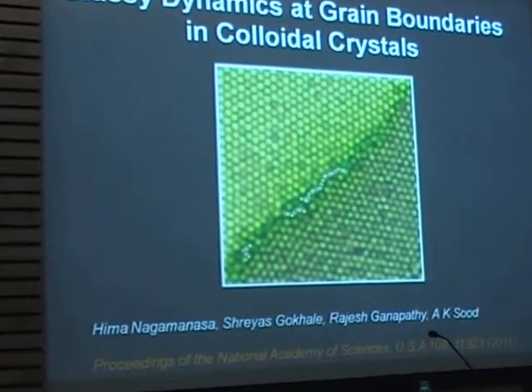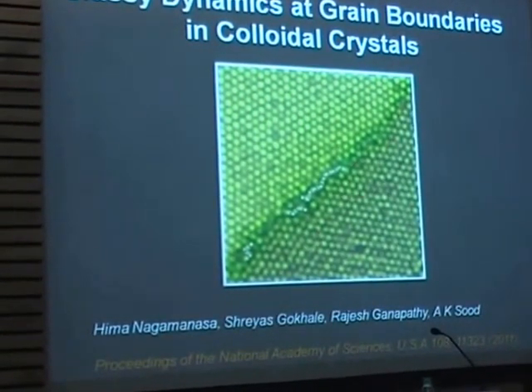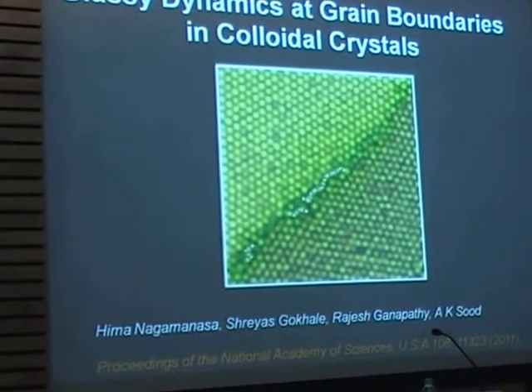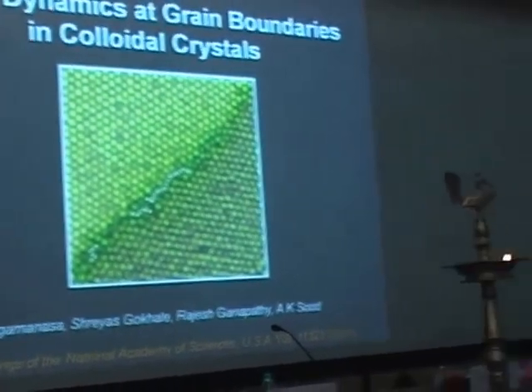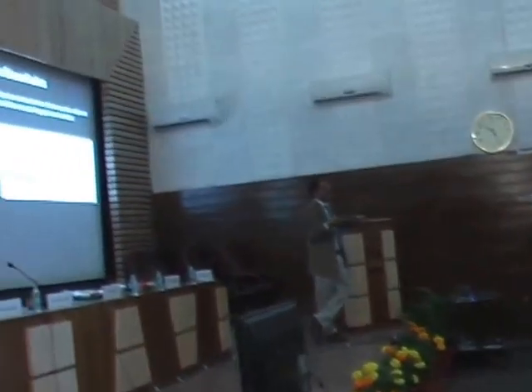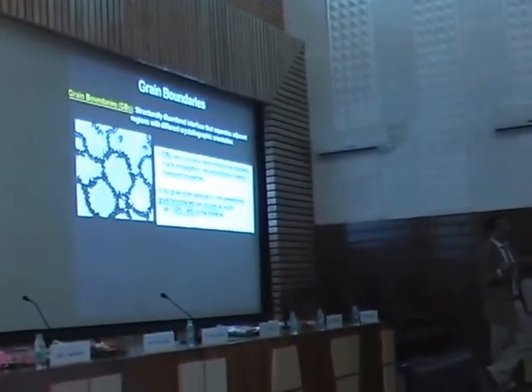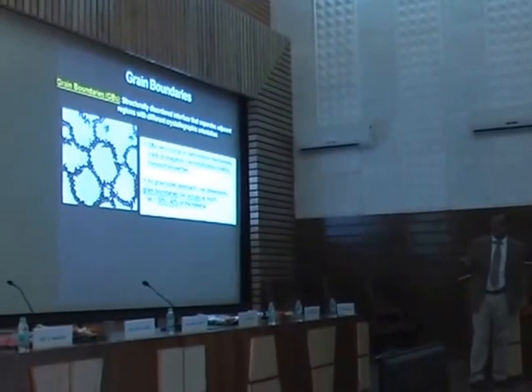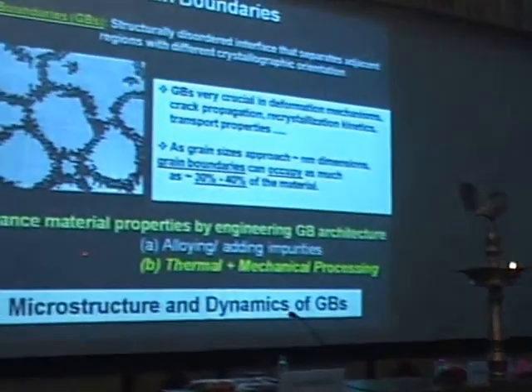That is the goal. So last year we showed that this grain boundary is very disordered, which is not surprising because you have one crystal and another crystal, and this grain boundary has all the properties of a glass. It is a glassy material, it is a solid, but a disordered solid. And this has very interesting ramifications on the behavior of grain boundaries when you shear it and so on. And this is what we have addressed. So the grain boundaries really decide the strength of the material. All the material which we use in our life has these grain boundaries.